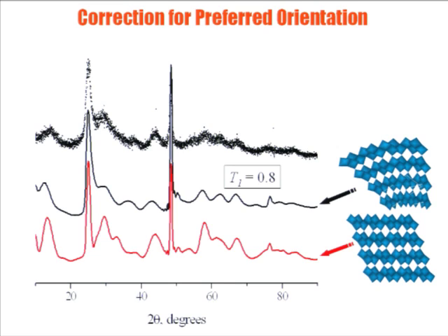But it was good enough for our purposes, because if we compare the pattern calculated from our non-uniformly deformed segment and ideal segment, we can definitely tell that this is not ideal. It provides a much poorer match to the experiment. And this actually has pretty important consequences. We can explain electrochemical properties of these materials much more readily using the deformed structure.